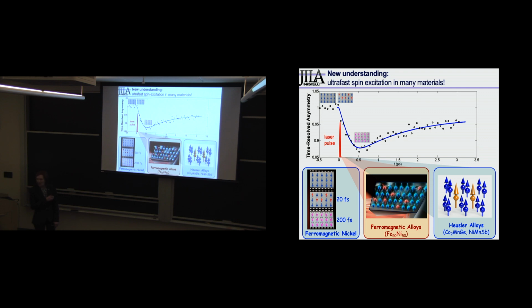And so, only when those exotic excited states relax, but even though it's not the right analogy, the latent heat from the laser goes in here. I know this is not, for those of you who, but it's just to get the idea across, that it's this relaxation of a high energy magnon state to a low energy magnon state that is propagated throughout the band. This is what the magnetic spectroscopies see. So that's why people missed it.